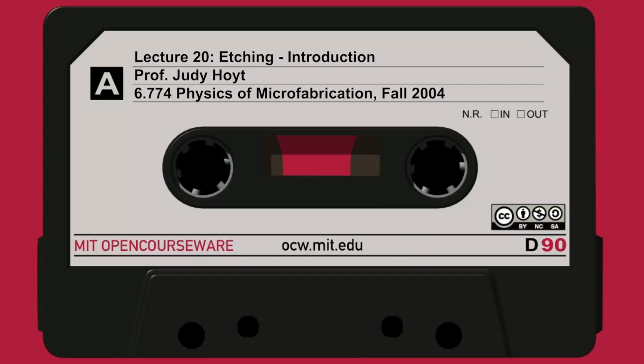Now, there's a second way to operate the parallel plate system, shown here on slide 23. Parallel plate in the RIE mode, reactive ion etching. In order to do this, we need to get more directed etching. We need to have a stronger ion bombardment. We need to have a higher voltage drop between the plasma and the wafers. So here you make the wafer's electrode much smaller than the outer electrode, than the other electrode.